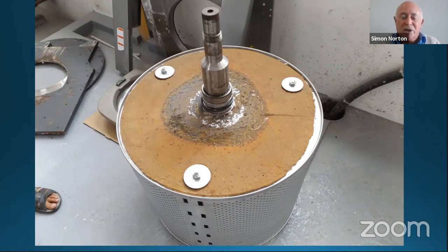And essentially it happens because two dissimilar metals are in an electrolyte and there's an electrical contact connection between them. And when those three conditions are met, electrolyte, two materials far apart on the galvanic series, and electrical contact, provided there is the right ratio of surface areas, you will get corrosion. So in your design, you have to be very, very careful. It is possible that in the case you see in front of you, the large stainless steel drum, which would have been passive and therefore noble, and the smaller mild steel disc, which would have been active and would be the anode, could have corroded because of a galvanic reaction.